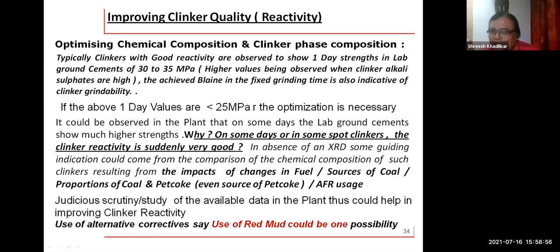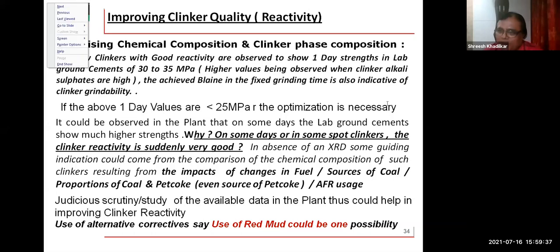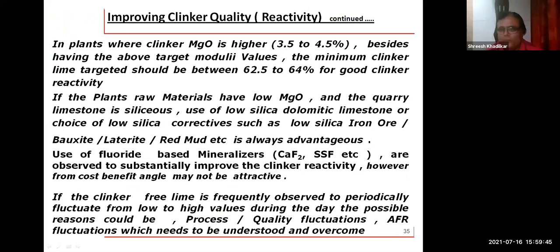Red mud is chemically similar to corrective materials used in clinker manufacturing. It is low in silica and high in alumina and iron. Using a low-silica material like red mud keeps the LSF of clinker higher, enhancing C3S phase formation and saving quality limestone from the mines. Reducing silica lowers the SM ratio and improves C3S content, increasing early strength. If activity at early ages is improved, you can absorb more fly ash in that type of clinker.